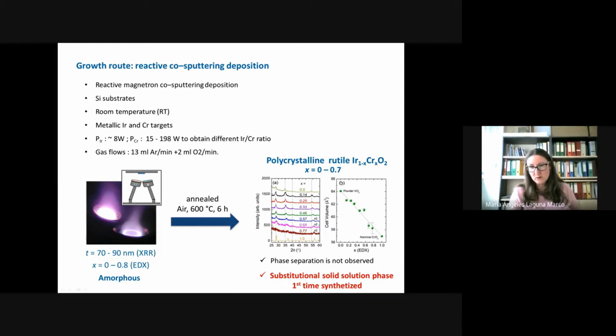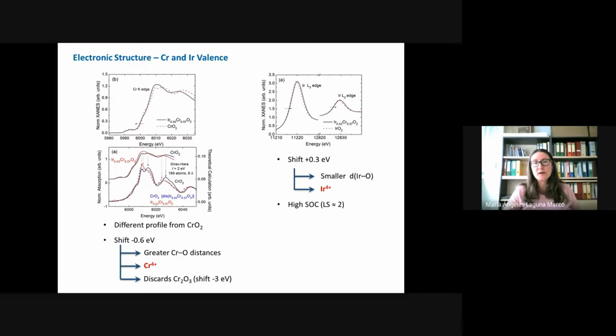As can be seen in the lower right figure, single phase with rutile structure can be obtained for all the films with a content of chromium between 0 and 0.7. In other words, the reactive sputtering has succeeded in stabilizing chromium in the rutile structure. The analysis of the X-ray absorption spectra allows us to conclude that both the chromium and the iridium present a 4+ oxidation state. Besides, the presence of chromium-2 oxygen-3 can be ruled out from this data.